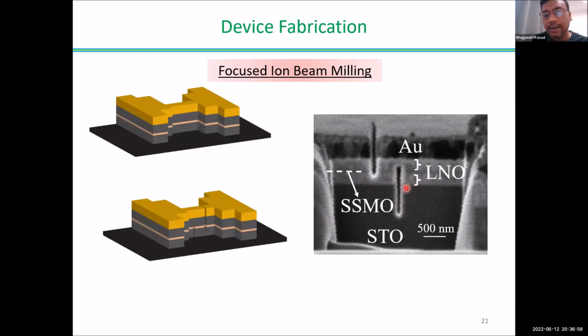This is cross-sectional TEM. What you see here is that the top and bottom is lanthanum nickelate. There's a thin black dot here, which is basically the SSMO barrier, and this is the top gold, which is sort of a contact for making some wire bond contact, and it also protects our sample during the fabrication process.